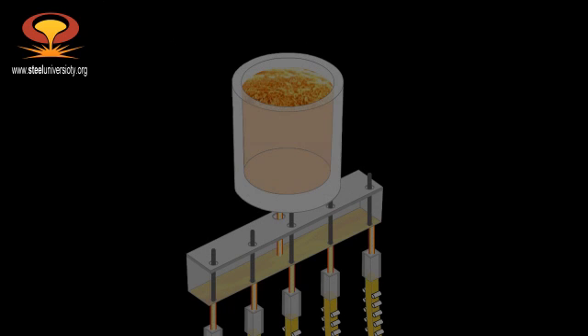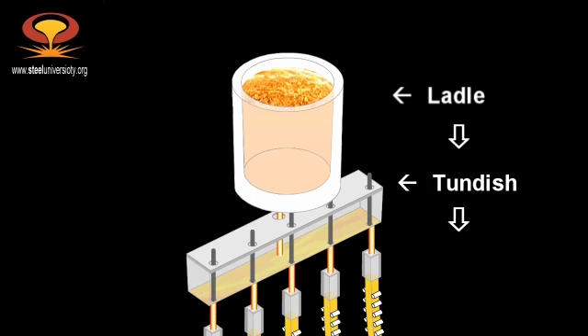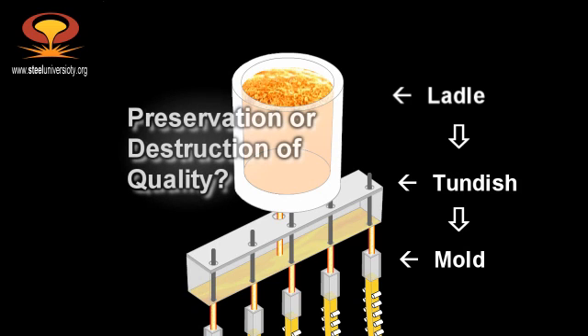When we think of transfer operations, we are thinking of transfer from the ladle to the tundish and from the tundish to the mould. During these transfer operations, vortexes can form in each of these reactors. For example, a vortex can form in the ladle, and particularly as the level of steel in the ladle decreases, that vortex can draw ladle slag into the tundish.